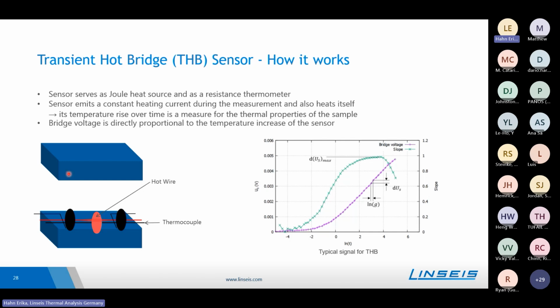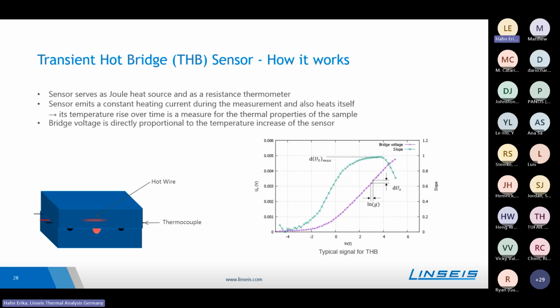During the measurement, the sensor serves as a Joule heat source and at the same time as a resistance thermometer. So during the measurement, the sensor emits a constant heating current and heats itself. Like shown here, we have the Joule heating, and during the measurement, the hot wire or the sensor will heat up the sample. The temperature rise of the sensor over time is then a measure of the thermal properties of the sample, so the surrounding material. But we do not measure this temperature rise directly, but look at the bridge voltage, which is directly proportional to it, and a typical signal will look like that.